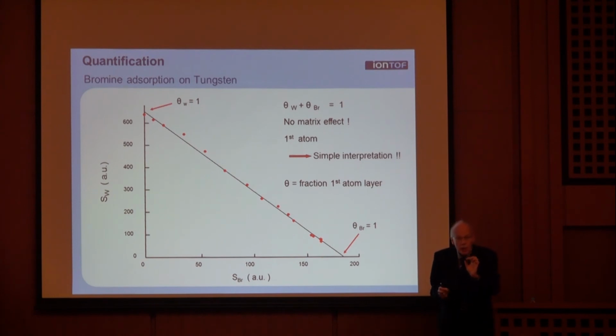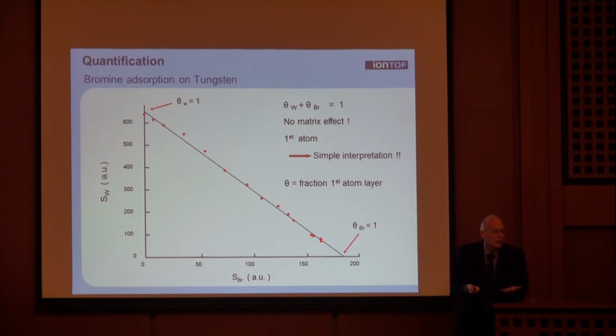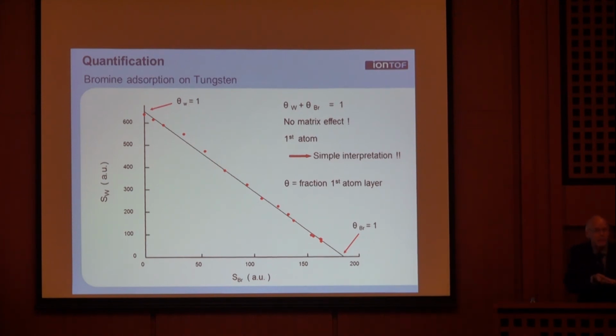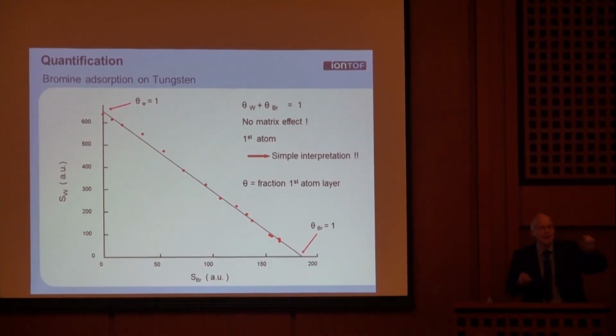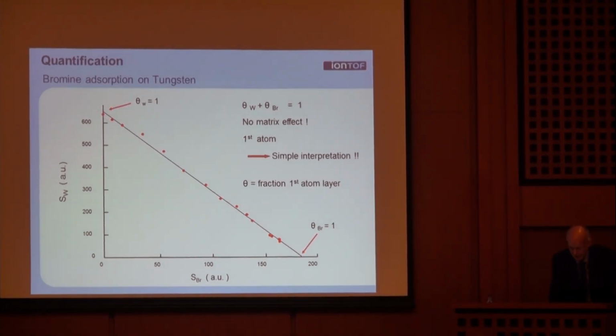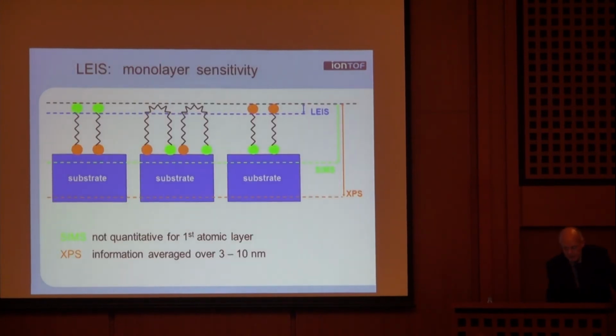Why? Because I look only one atom deep. So at the surface it is either tungsten or bromine. So the coverage of tungsten plus bromine is 100%. I call it 1. And so if there is less tungsten, there must be more bromine. And that kind of quantification makes it so very simple, because you don't have to think about contribution from second, third, 20th atomic layer. It's just everything going on in the top layer.